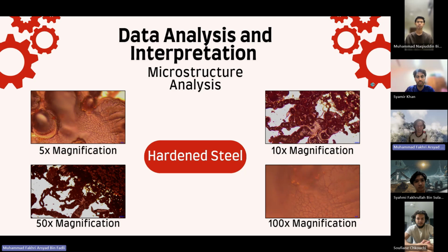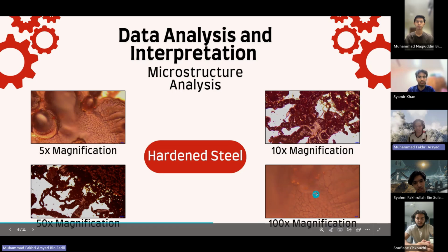Analysis and interpretation. From our given data, we have been given 4 types of magnification: 5 times magnification, 10 times magnification, 50 times, and also 100 times magnification. From the pictures given, we did our research, and the 10 times and 50 times magnification show that the material has a botryoidal shape, which is grape-like. And for the 100 times magnification, we can see that there are marked cracks on the material.